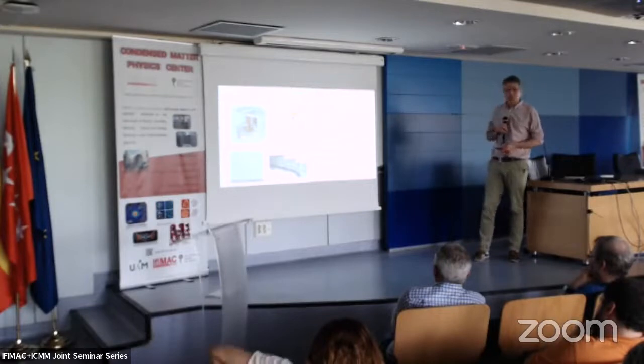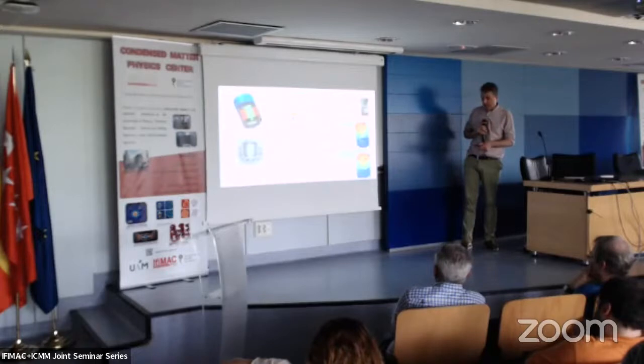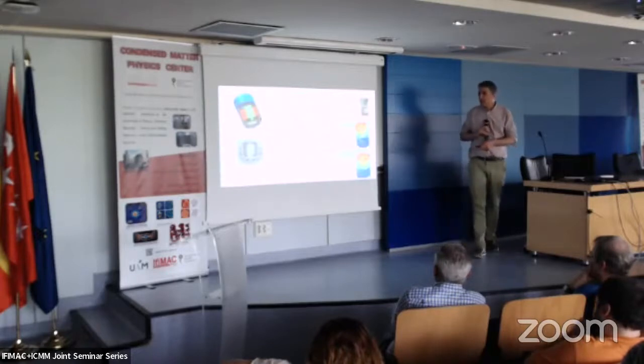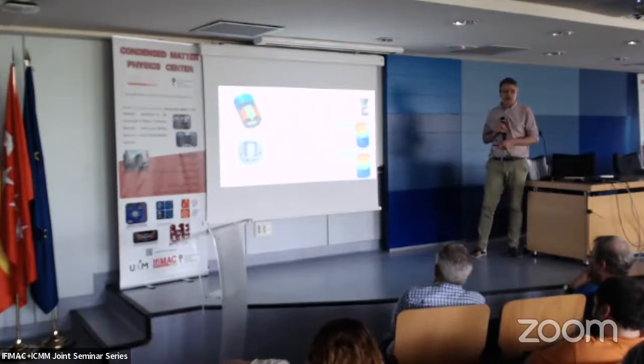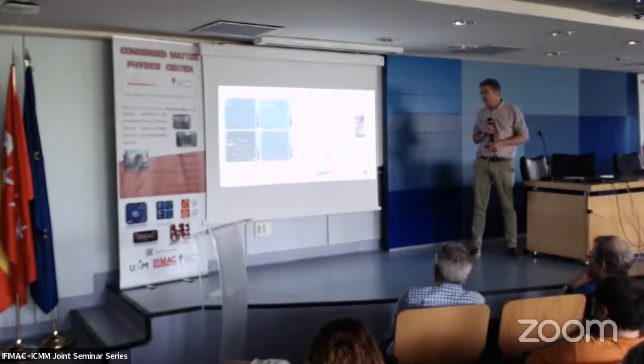And this is what we find when we take a look, for example, in aluminum. We have here the spectrum, which has no states inside the superconducting gap, and with this we can study superconductors. We need to go to very low temperatures and to have a high resolution in energy, and for this we have to make the hardware and the software ourselves in order to be able to do that.